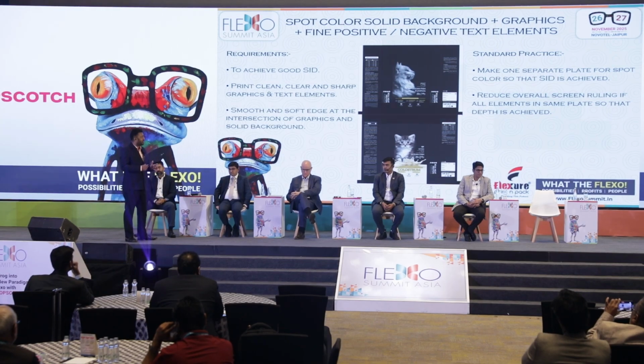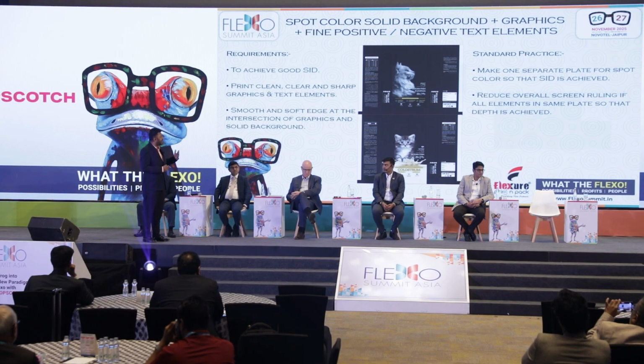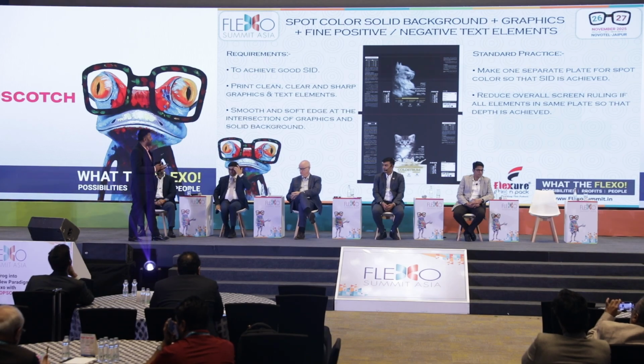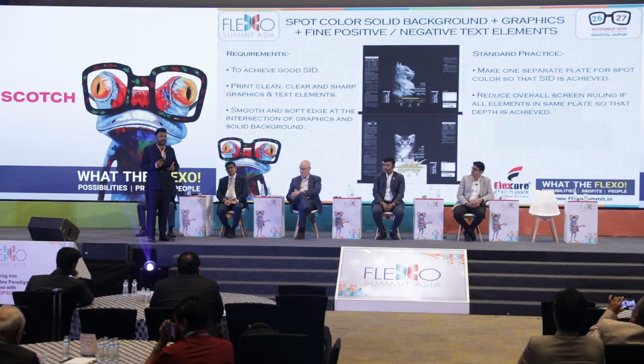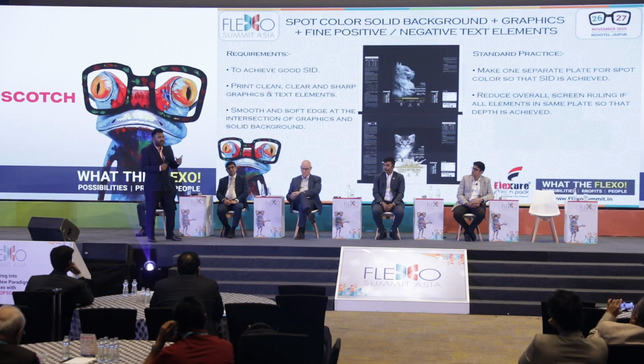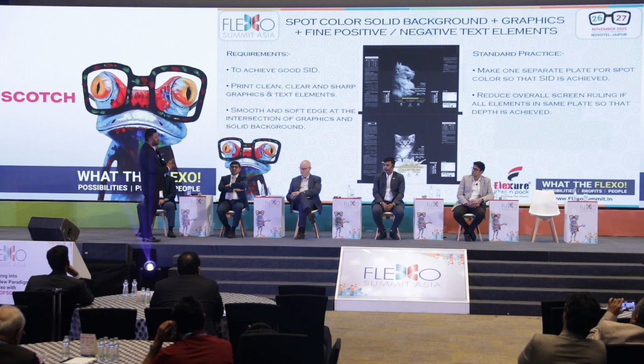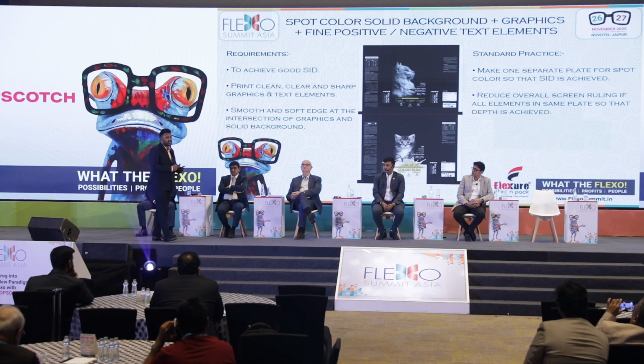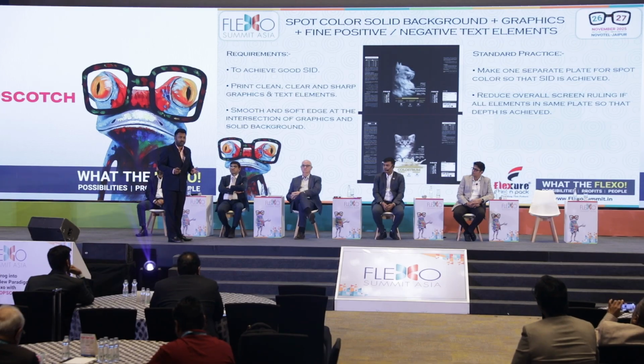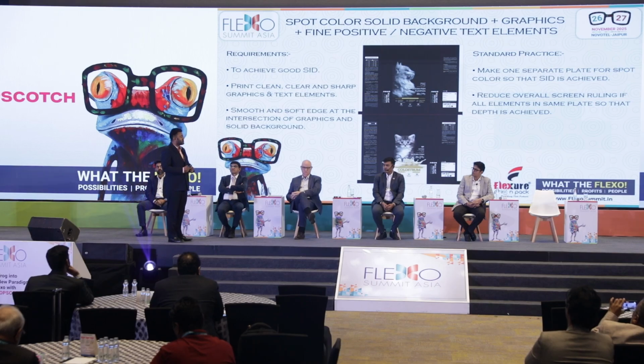Moreover, if you change the anilox for, let's say, background spot color and halftones, we don't get a very smooth intersection, because the volume of anilox is different. We are printing solid with a coarser anilox and halftones are printed at finer anilox. So we see a hard edge when they intersect. Normally we want to have a smooth intersection. So how do we do this? The normal standard practice is to make a separate plate for spot color so that the solid ink density is achieved, and halftones in a separate plate so that the halftones are well managed.